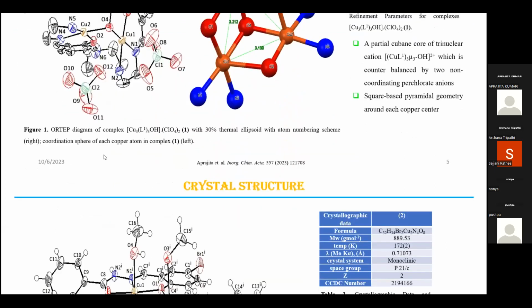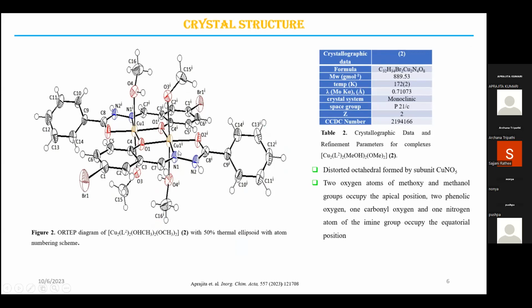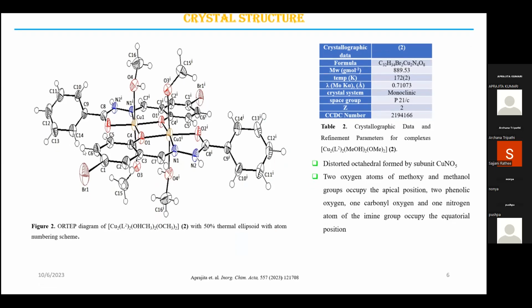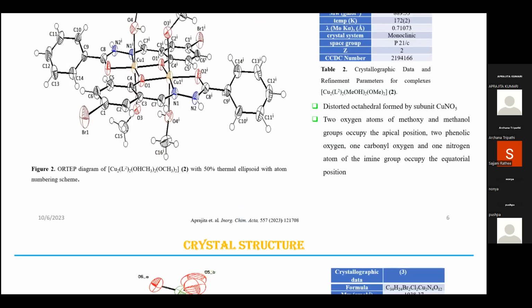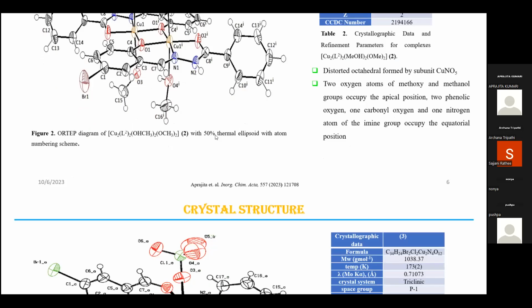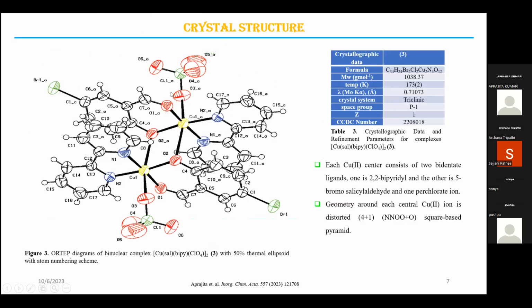Figure 2 shows the ORTEP diagram of the second complex, where a dinuclear complex was formed. The geometry around the copper center is distorted octahedral, where the square base is formed by the tridentate Schiff base ligand, and at the end positions there is one methanol molecule and one methoxy group. Here also the axial bond was longer than the equatorial bond. This is the crystal structure of the third complex, a dinuclear copper complex, directly formed using 5-bromosalicylaldehyde and 2,2'-bipyridyl. The perchlorate was found attached axially to each copper atom, and the geometry around each copper atom is square-based pyramidal.